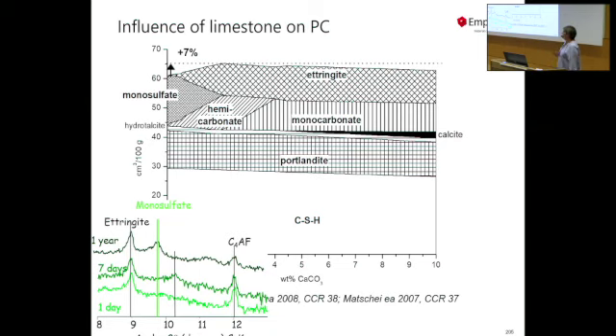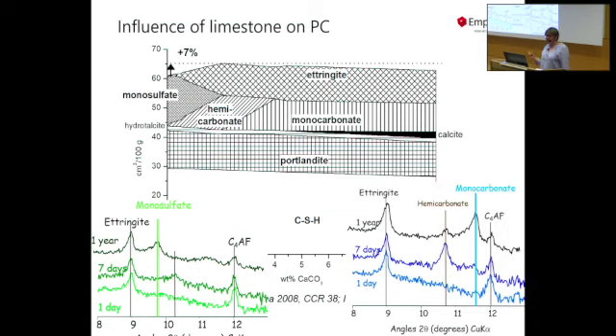But first let's check whether this makes sense. On the left-hand side in green I put an XRD of the samples, and we see ettringite and monosulfate. If we look at a sample which contains 4% of limestone, then in fact we see monocarbonate instead of monosulfate and more ettringite, confirming what we predicted. Otherwise I wouldn't show it, to be honest.